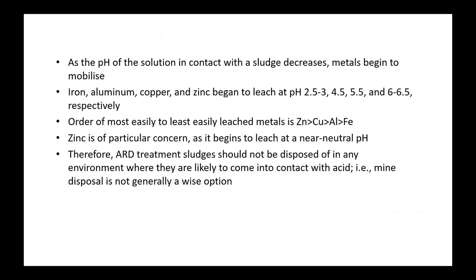Next slide. So, if these sludges come into contact with acid solutions, they will release the metals. And you can see the different pHs at which they're approximately released there. And zinc is the one that's released at 6.5, which is not much below neutral pH. So you can see that zinc is particularly easily leached. So really, the results of his study showed that it's not a good idea to put the treatment sludges back anywhere they're likely to come in contact with acid, because you'll get the metals back into solution and then you'll have to treat them all over again. So this limits disposal options to somewhere not in the mine. Next slide.